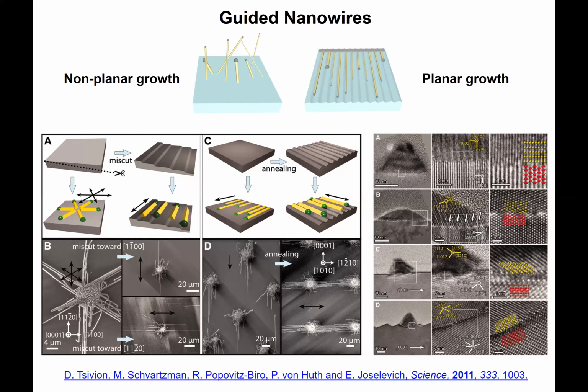And they can, if the surface is atomically flat, then the nanowires usually follow certain lattice directions due to an epitaxial effect. So it's related to atomic registry.